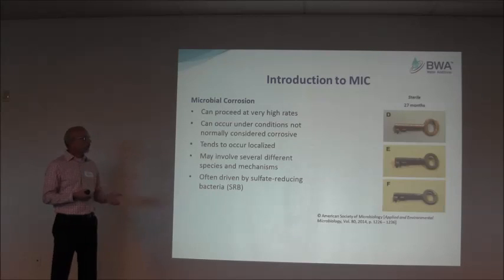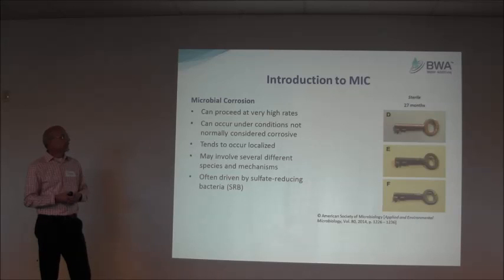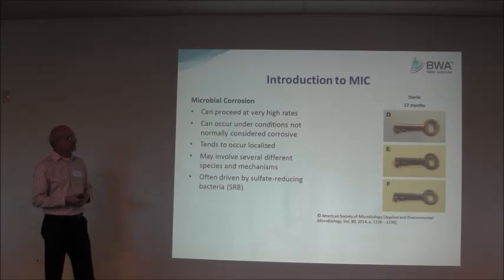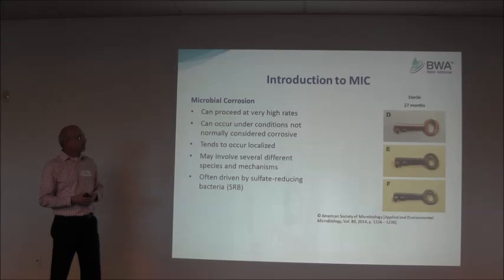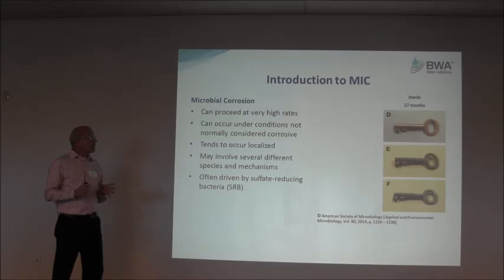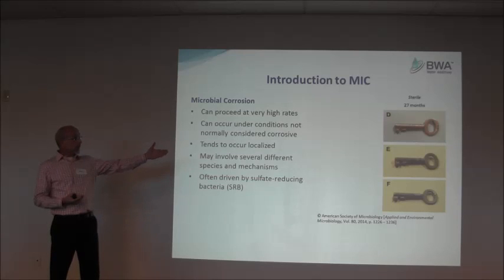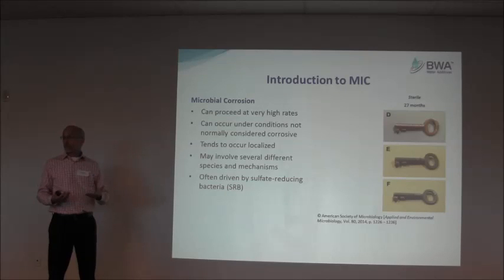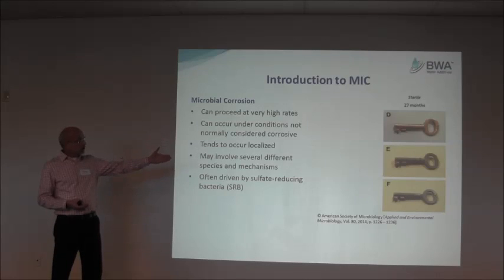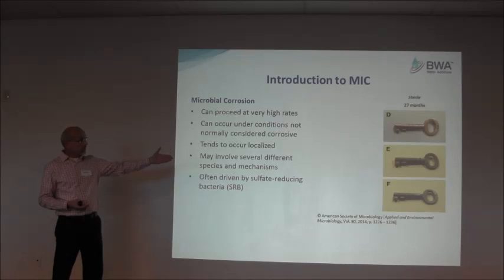Here's an example comparing different mechanisms of corrosion. On the left you can see an iron key in a sterile, deaerated seawater medium. Steve was talking about corrosion that happens with oxygen, and it was very rapid. But under anaerobic or anoxic conditions, corrosion proceeds at a very low rate — here's 27 months of this iron key in salt water with relatively little corrosion occurring.